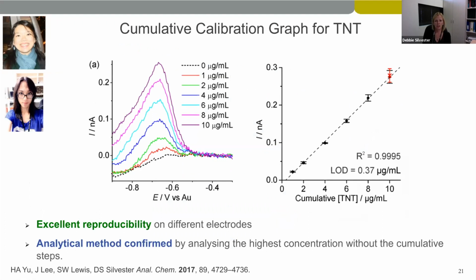And we use a cumulative calibration method because once the TNT goes into the ionic liquid, it does not want to come out again. So in this case, we added 1, 1, 2, 2 micrograms per mil in the aqueous phase, and then we continually added the TNT into the gel. And you can see this calibration graph with the error bars for 3 repeat measurements. So very reproducible. And then just to confirm the method, we looked at the highest concentration just by itself with no cumulative methods. And you can see it overlays the 10 microgram per mil response very well. So this was a new way to detect TNT or other explosives in water samples using liquid-liquid partitioning.